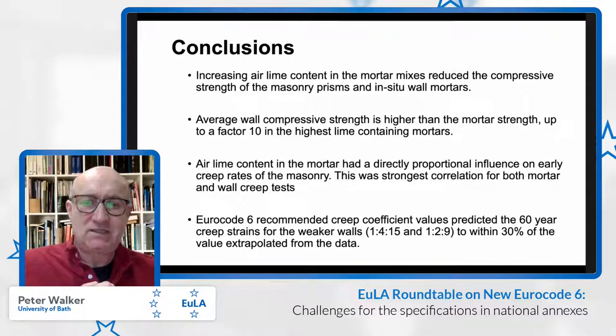for both the mortar and the wall creep tests. And we found that the Eurocode 6 creep values predicted, we only measured up to, I think 8 months was the longest period we measured for the wall tests. But from that, we sought to extrapolate the creep strains for longer term. And the values were within 30% of what we were able to extrapolate.